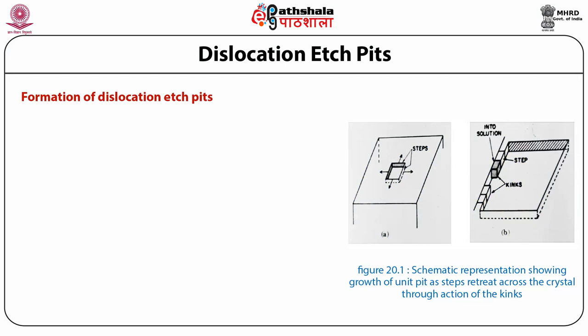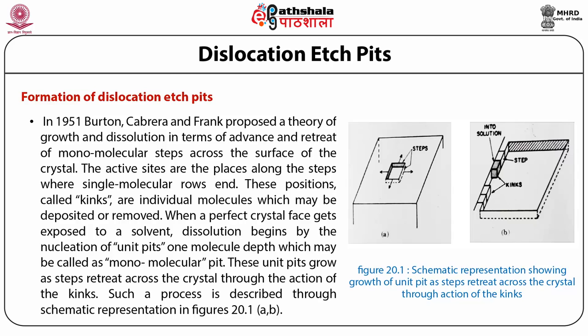Formation of dislocation etch pits: in 1951, Burton, Cabrera and Frank proposed a theory of growth and dissolution in terms of advance and retreat of mono-molecular steps across the surface of the crystal. The active sites or the places along the steps where single molecular rows end — these positions called kinks — are individual molecules which may be deposited or removed. When a perfect crystal face gets exposed to a solvent, dissolution begins by the nucleation of unit pits, one molecule depth, which may be called as mono-molecular pit. These unit pits grow as steps retreating across the crystal through the action of the kinks. Such a process is described through schematic representation in figure 20.1 A and B.